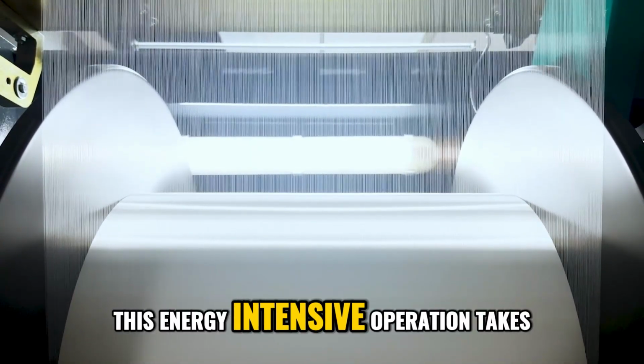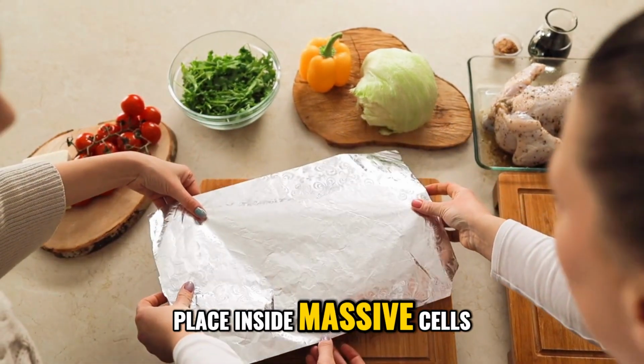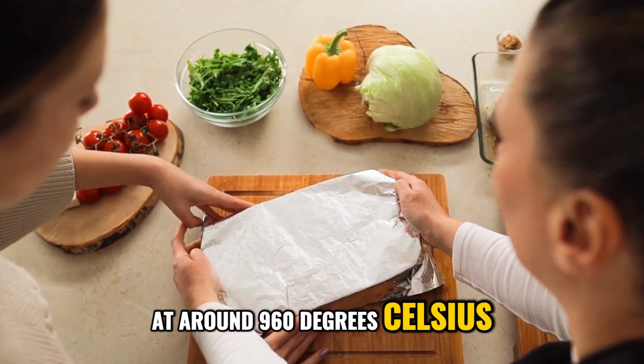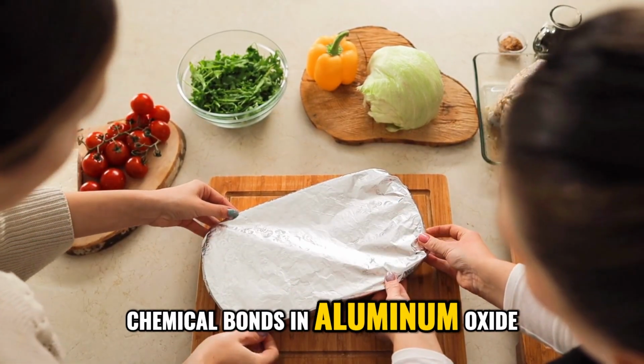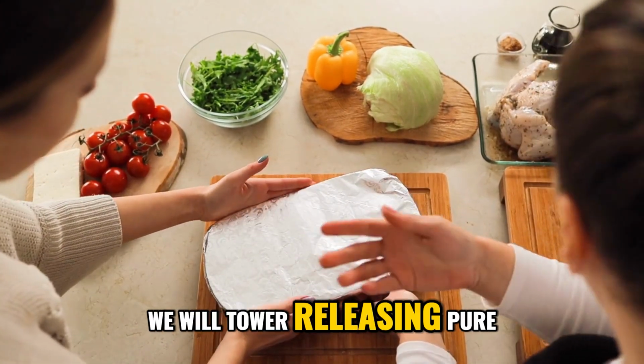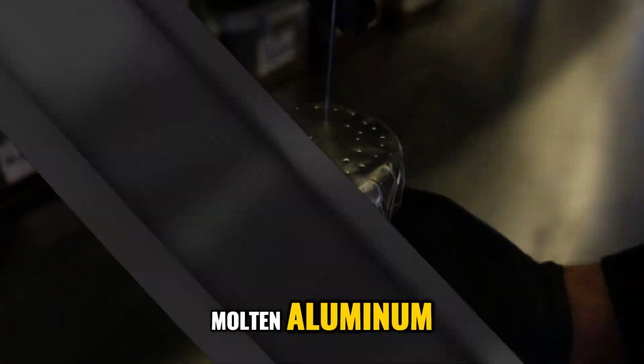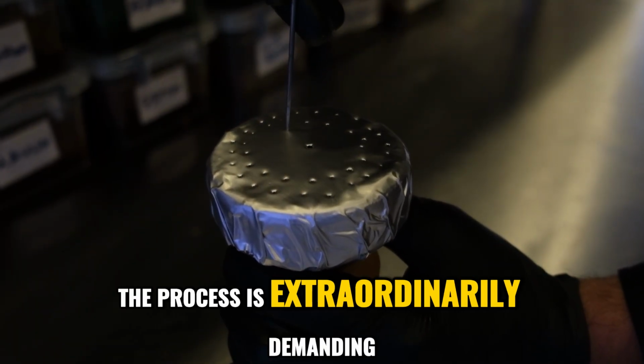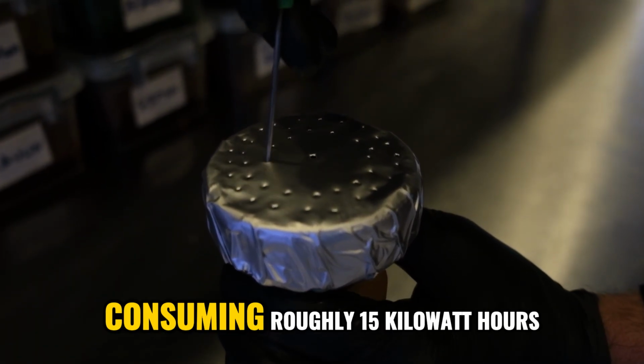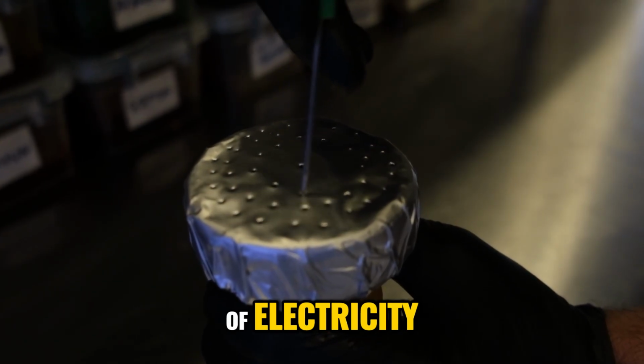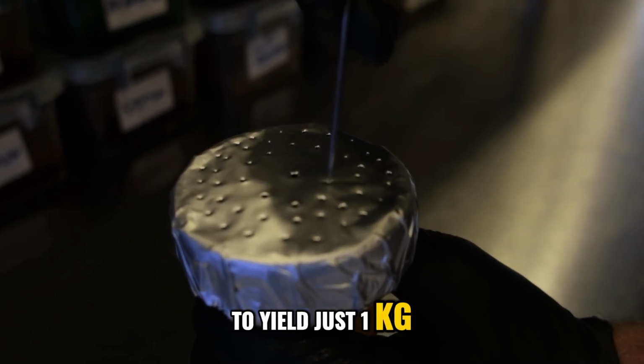This energy-intensive operation takes place inside massive cells filled with molten cryolite at around 960 degrees Celsius. Powerful electric currents sever the chemical bonds in aluminum oxide, releasing pure molten aluminum. The process is extraordinarily demanding, consuming roughly 15 kilowatt-hours of electricity to yield just 1 kilogram of aluminum.